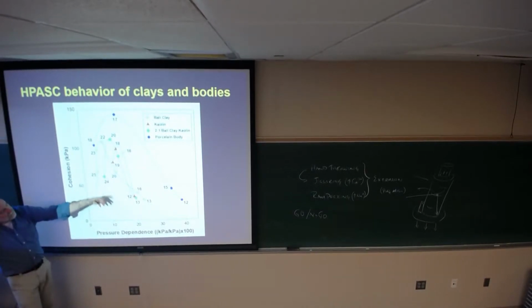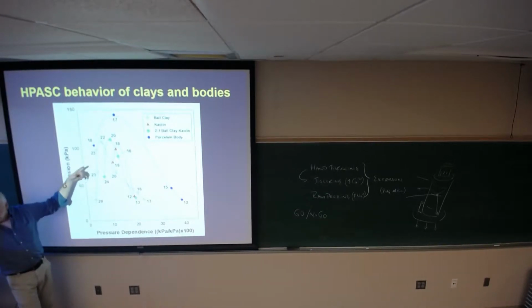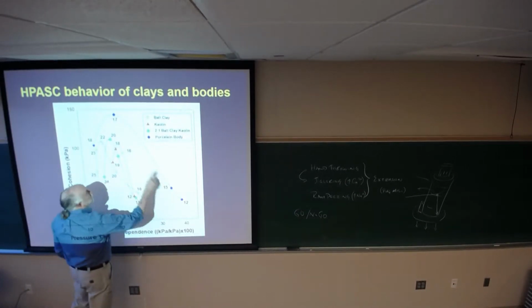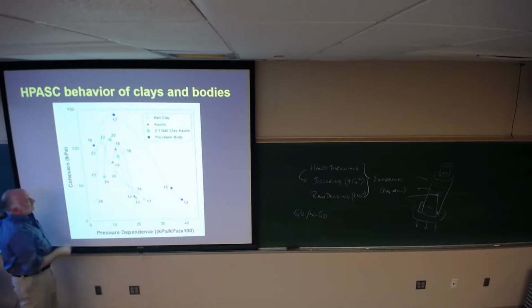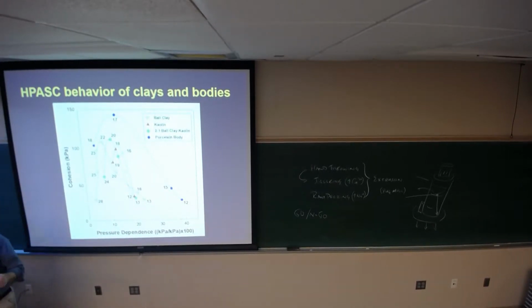And then look at a typical porcelain body. Water content is significantly lower for that porcelain body where you get the peak. So 12, 15, 17, and then 18. We're coming back down. If you go to 20, you're down here someplace. Why? Why do I require a different amount of water to saturate a porcelain body versus clay? What do you think, Ian? Difference in surface area? Not surface area. Adam? What's the difference between just a clay and a porcelain body?